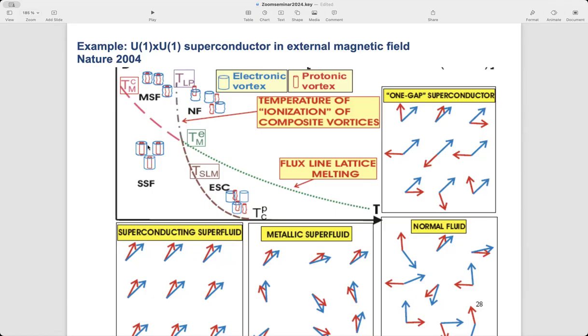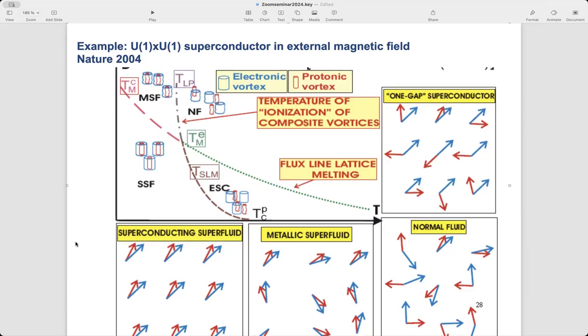Or there could be an interesting, and more natural, phase transition, where one melts this vortex lattice without tearing two fractions of the flux quantum away from each other. And in that case, you still retain broken symmetry. If one denotes phases by arrows, then that state, which we call metallic superfluid, is a state where there is order in the phase difference between components, but each of these components individually is not ordered. So this electronic vortex actually carries the heavier, larger fraction, and this protonic vortex carries the smaller fraction. So that was the proposal.